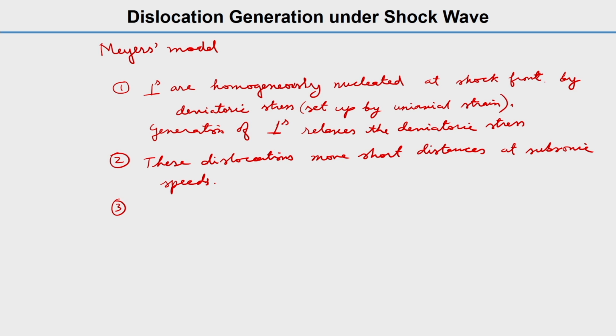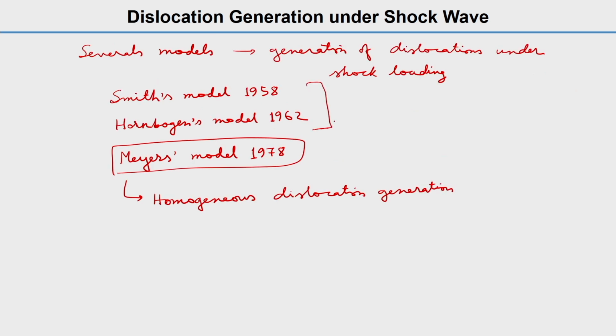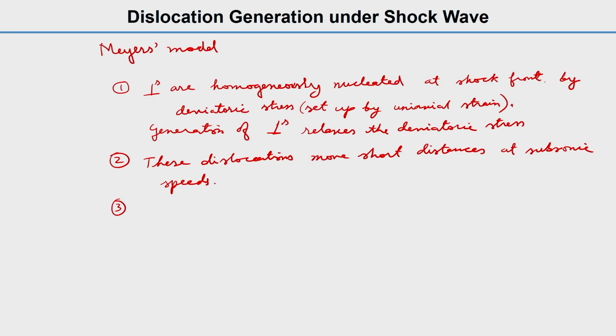So, why are we discussing here Meyers' model, and not Smith's and the other Hornbogen models? Because they have several limitations. These models have several drawbacks, and there are more models, so we are not discussing them, and we are not discussing much of what is not there in Meyer's book. But the early models have several drawbacks, and Meyer's model tries to address that. Especially, this model talks about subsonic speeds, but according to Smith's model there are some supersonic dislocations, and that was eliminated by Meyer's model. And number 3 is new dislocation interfaces.